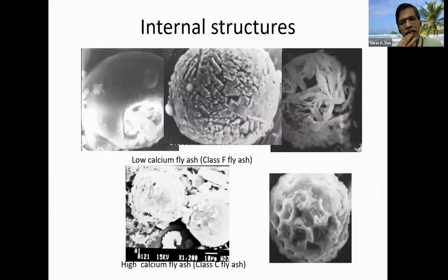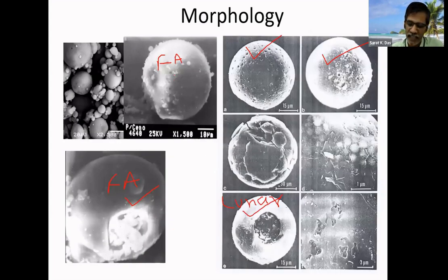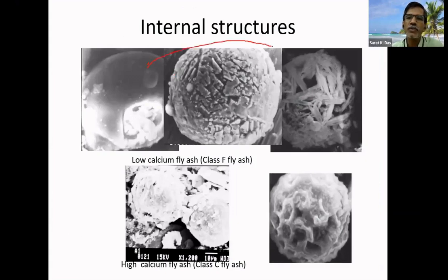Then what I tried, as I said, if you see this structure, which we call a plerosphere, and that is mostly in the class F fly ash. This fly ash has some particles like this or some particles like this. I dissolved it using hydrofluoric acid just to take out its skeleton. This, as I said, is the internal structure; to look at that, this was how the internal structure is. So that means this cover is an aluminosilicate glass structure. That's why it dissolved using hydrofluoric acid.